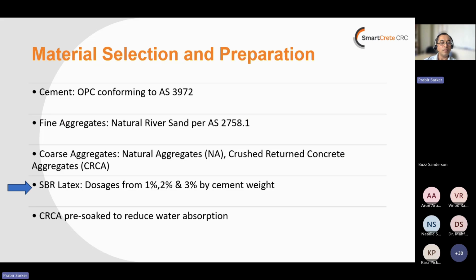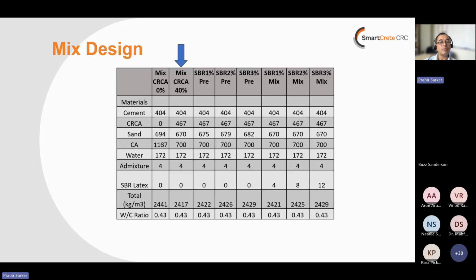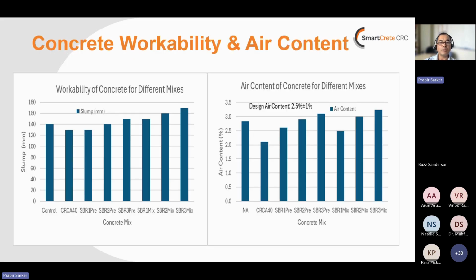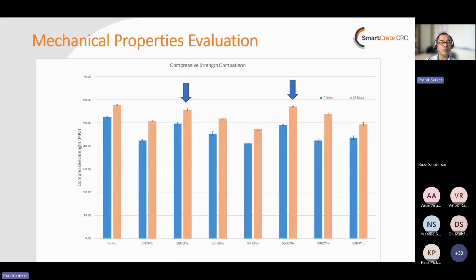So Riyadh has been trying this 1%, 2%, and 3% SBR latex. That is the percentage of the weight of the cement, adding in two different ways, pre-mixed and during mixing. So these are the mixed proportions of concrete using 40% CRCA with 1%, 2%, 3% premix, and 1%, 2%, 3% SBR latex during the mixing of the concrete. So some of the results, okay, these are the workability and air content. It has some effect. More importantly, if we look at the effect on mechanical properties.